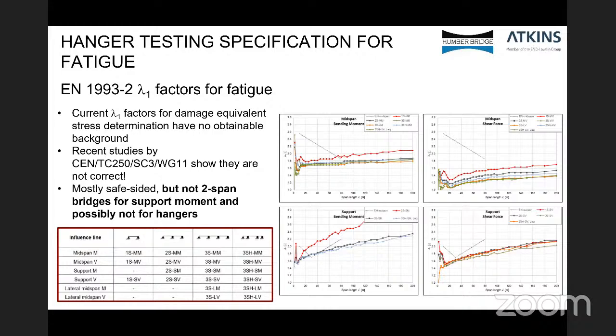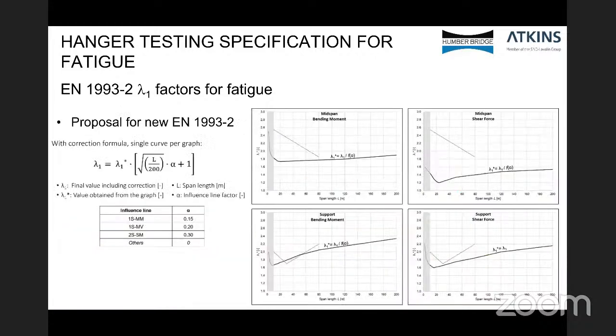If you look to the next, the concerns that they found was that mostly the FLM3 was conservative, but in certain instances where there were long influence lines, particularly for two-span bridges, the gamma factor wasn't conservative. In our instance, the Humber Bridge had a very long influence line because it's a cable supported structure, and so we had concerns that, in the initial test that we did, the lambda factor wasn't appropriate. If you look to the next slide.